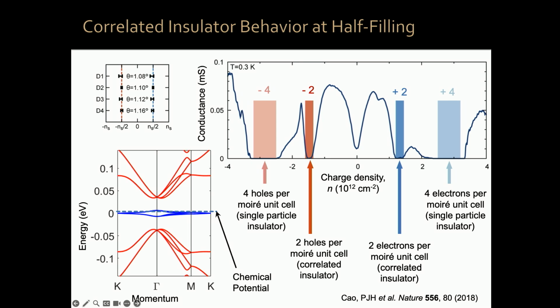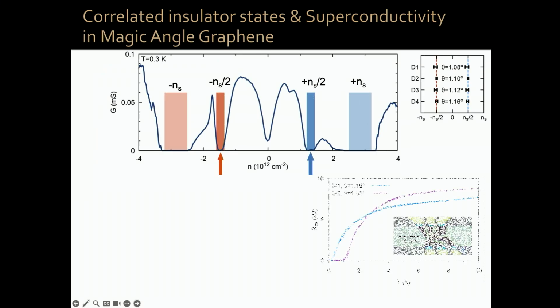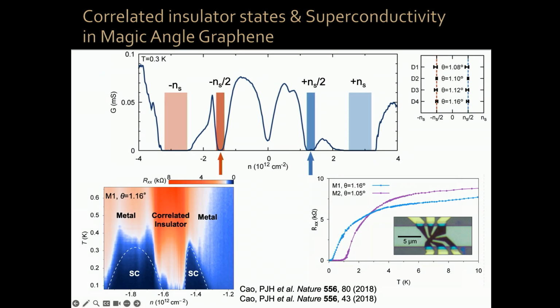And then what was an even bigger surprise that we found is that if you now add a few electrons or a few holes to the correlated insulator state, your system turns into a superconductor. An electrically tunable superconductor, in fact. At certain density, you have correlated insulator states. You add more electrons, you have superconductivity. In this case, you add holes, you have superconductivity. So magic angle twisted bilayer graphene is an electrically tunable superconductor. A superconductor you can switch on and off.